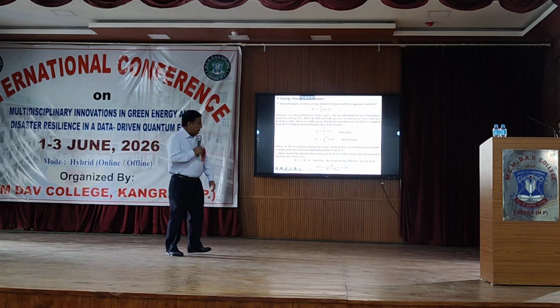This is for recoverable energy, which we can calculate just by measuring the PE loop at different temperatures, and of course the difference between these is the loss, and efficiency is calculated by this formula, but you can understand it very well in the next slide.